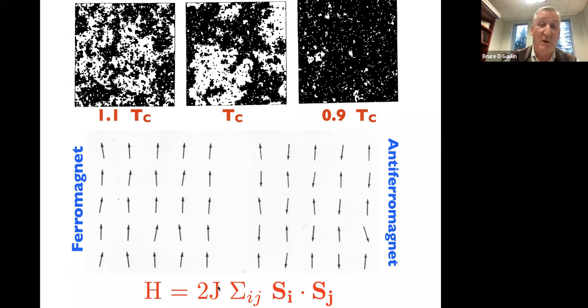Depending on whether J is positive or negative, you can lower the energy either by having near-neighbor spins align parallel to each other, as they do over here on the left, or anti-parallel to near-neighbors, as they do on the right. Of course, that's either ferromagnetism or anti-ferromagnetism, and this will occur at low enough temperatures. What happens as a function of temperature in most conventional materials is represented by these 3 plots at the top, which are classical Monte Carlo simulations of a 2-dimensional Ising model. So these are spins that can only point up or down, and we can represent the up spins as a black square and the down spins as a white square.